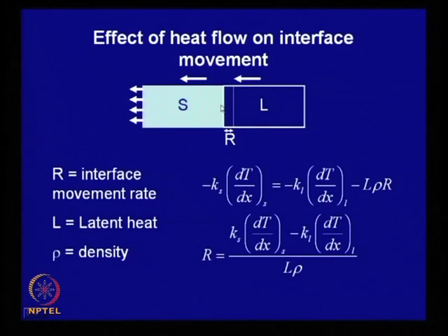When heat is extracted, there will develop a solid liquid interface, and this interface will progress as more and more heat is extracted. This interface will progress this side, and the evolution of structure depends primarily on the nature of this interface. For some of the calculations we do assume that this interface is planar, but a planar interface is not always stable, and it depends on several factors, not only on the heat extraction, it also depends whether there is supercooling in the liquid or not.